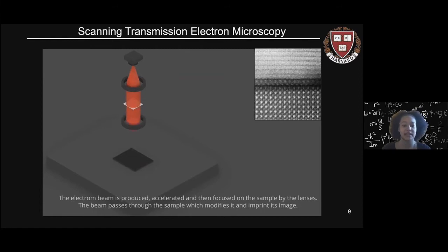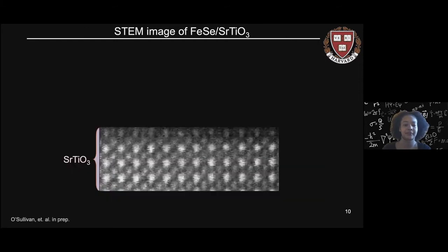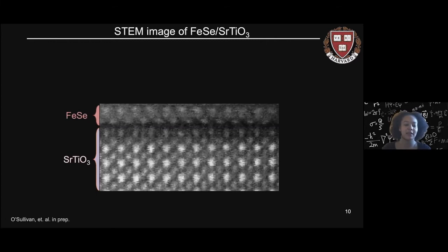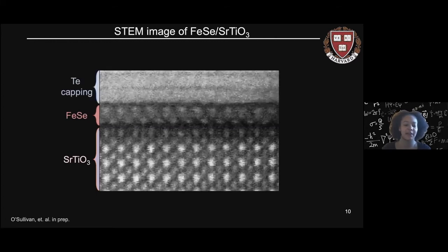So this is the actual STEM image that we were able to produce using our electron microscopy. Here we start with the bulk of our strontium titanate, and this animation describes the MBE growth approach, where we then deposit a monolayer of iron selenide and finally a capping layer of tellurium. So you'll note here this STEM image has atomically clear resolution, over which I will overlay a crystal so you can see exactly which atom belongs to which element. Note that we do not see an ordered layer of selenium in our STEM, which was our first research question. There's no excess selenium between the monolayer of iron selenide and the bulk of strontium titanate.